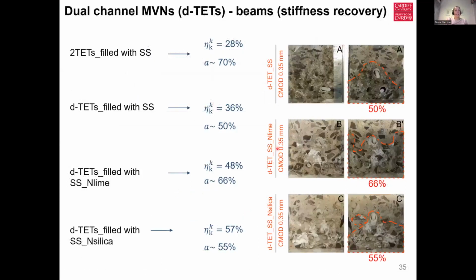With most of these healing systems, especially when we're using sodium silicate, we actually tend to get better stiffness recovery than we have from our strength recovery. So we generally tend to get upwards of 45–50% when we consider our stiffness recoveries. And that's been confirmed by, again, what we can see on the screen now. And again, there was good evidence of release of the healing agent on the crack surface. So anywhere between 50% of the crack surface was covered with the healing agent, up to about 66% in the case of the sodium silicate with nanolime that we see in the middle here. So evidence of not only healing, but also stiffness recovery and flow on the crack face.